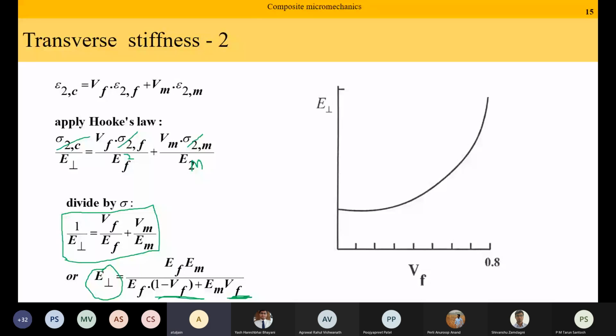So, very good question. I think this is something that you have to be very careful about. If your fiber's property is different in the 1 and 2 direction, while calculating the transverse modulus of your composite, the correct value is going to be the modulus of the fiber in the transverse direction. For example, in our previous lecture, we found out that carbon fiber has high modulus in the fiber direction, not so high in the transverse to fiber direction. So we have to put the modulus of the transverse to fiber direction while calculating the transverse stiffness of the composite. Okay, good. Any more questions?